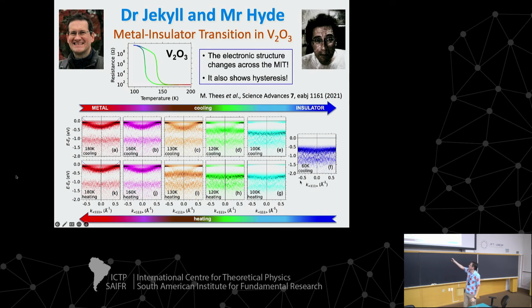So this state is transferring spectral weight to this state, and eventually, at 60 Kelvin, the only thing that remains is this quasi-localized state with a gap of about 600 millivolts and no signature anymore of the quasi-parabolic state. And when we warm up, the opposite thing happens with a clear hysteresis in the electronic structure, which is beautiful. To my knowledge, this is the first time a clear hysteresis in the momentum-resolved electronic structure of a